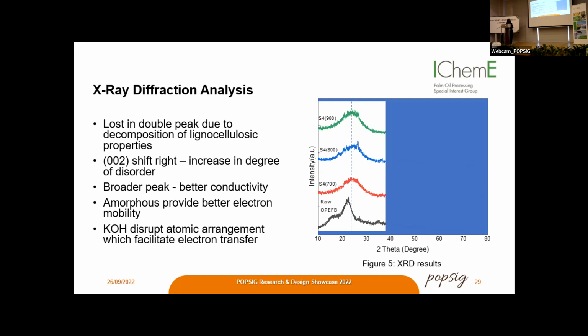Not only that, samples carbonized at 800 degrees have a broader peak than the other samples, which means that it is amorphous, and amorphous is preferred as it provides better electron mobility. KOH disrupts the atomic arrangement, which facilitates the electron transfer.